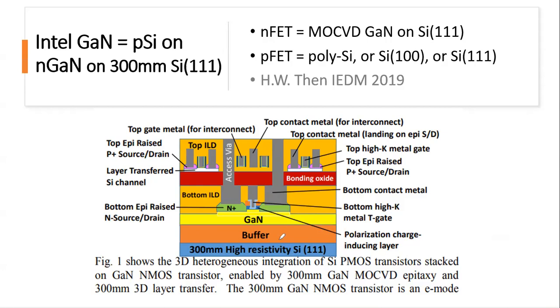First of all, the epitaxial growth of gallium nitride with a buffer, a couple micron buffer. Then about 4 to 6 micron, and then you put gallium nitride on top, and then you build your device. This is high-K metal gate. When you finish your NFET, you want to put a P on top. How do you put a P on top? There are three options: polysilicon, silicon 100, or silicon 111. So this is what we're going to talk about. And of course, the goal is to bond them with a bonding oxide, a layer transfer, or another SOI, or something. Let's go one by one.